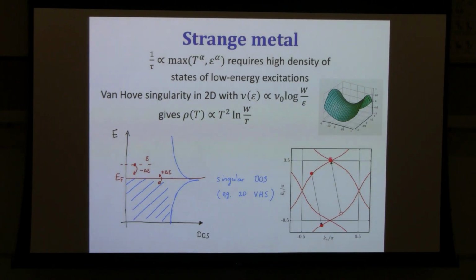So close to this point, the electronic dispersion looks like a saddle. Okay, so it's a saddle point in the energy momentum relation of the electrons. And close to that point, in two spatial dimensions, it turns out that the density of states actually diverges logarithmically. So suppose that our Fermi energy somehow can be tuned to be very close to this log divergence in the density of states. Okay, so then we'll have a lot more phase space to scatter electrons.